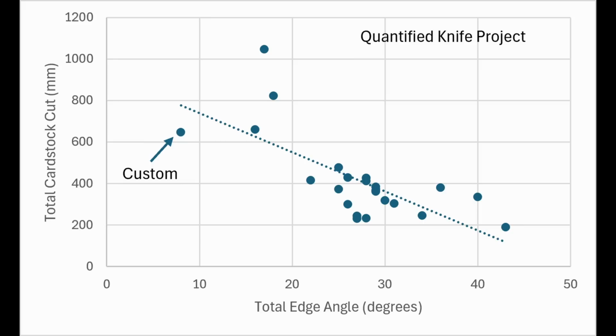And the rest of the steels, VG10 is higher wear resistance than AEBL and 13C26, and we tested quite a few VG10 knives, and also the lower wear resistant European steel 1.4116 at 56 Rockwell or so, and they all line up on a similar trend line here.